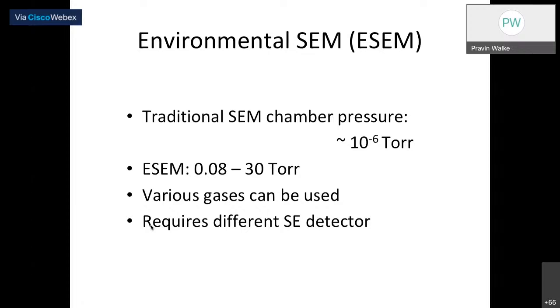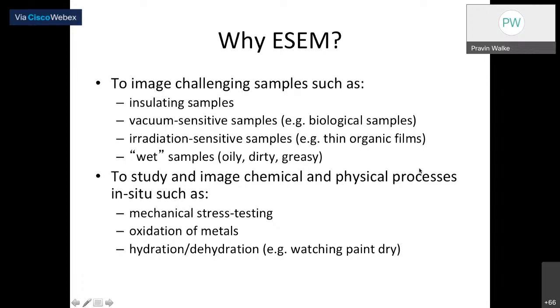So traditionally the SEM chamber pressure is 10 to the minus 6 torr. That is in the traditional SEM system. But if you go to the environmental SEM system, the pressure is increased and it comes to 0.08 to 30 torr. So very low vacuum pressure inside the chamber, and that SEM gets operated under various gases, as well as it requires different SE detectors. So what is the advantage of having that low pressure SEM, or low vacuum? Why is it called environmental SEM? Because it has this very low vacuum, right? So what is the use of having this SEM? ESEM.